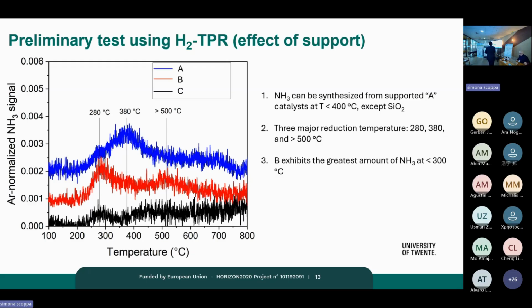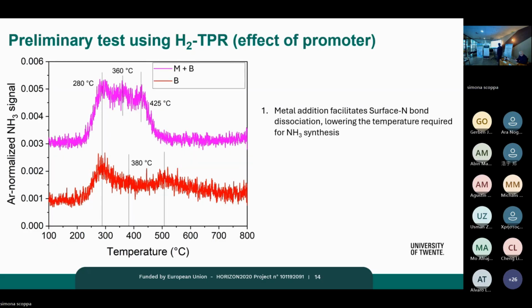And you see that there is evolution of ammonia for conditions that are otherwise very difficult to activate nitrogen bonds. In this case, this ammonia is from nitrogen or oxygen vacancies that are being generated by hydrogen. You don't have a hydrogen dissociation function here. Yeah? So that's a very, very interesting point. Now, if you add a metal functionality, which I cannot tell you exactly which metal it is or anything about its size, I'm sorry about that, you now can actually activate a much larger fraction of your metal nitride and evolve a greater amount of ammonia.